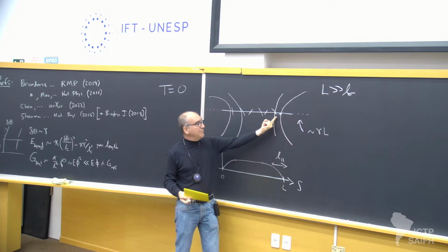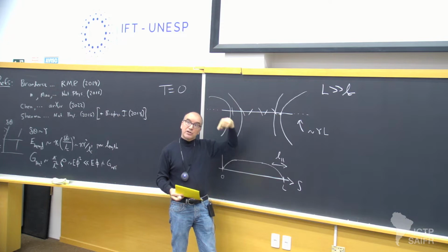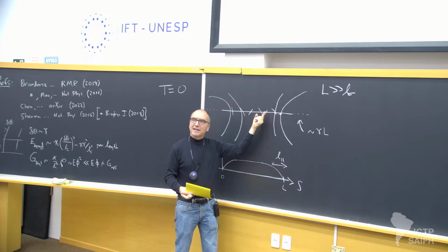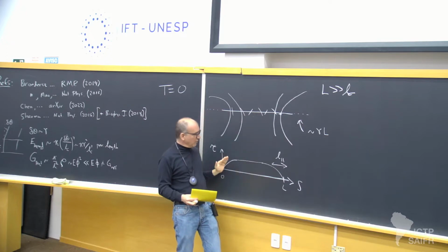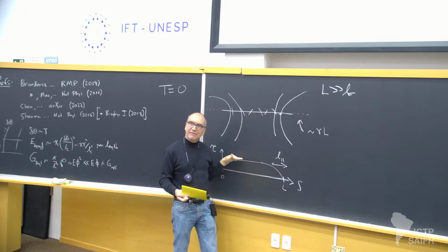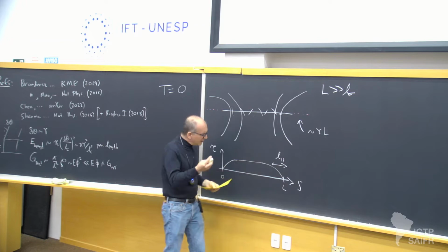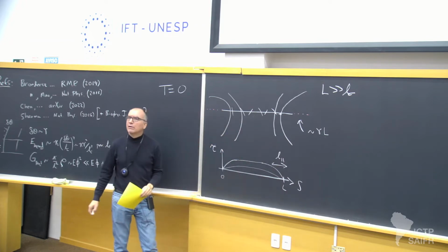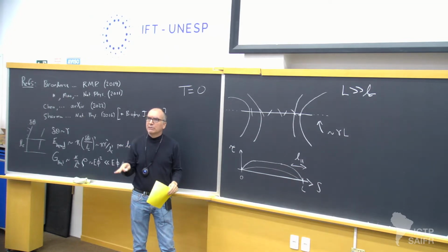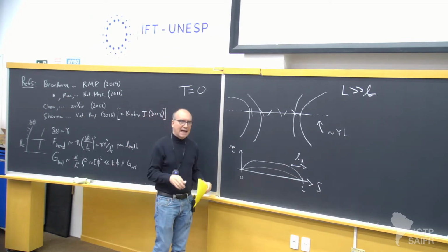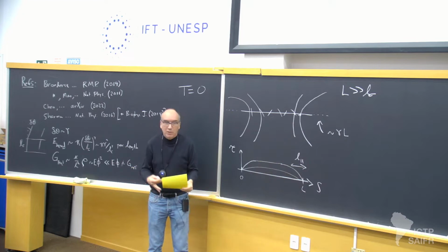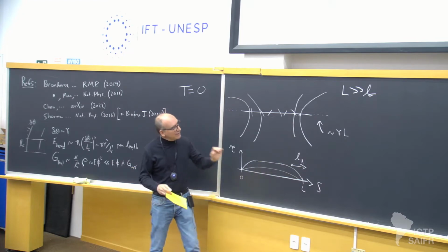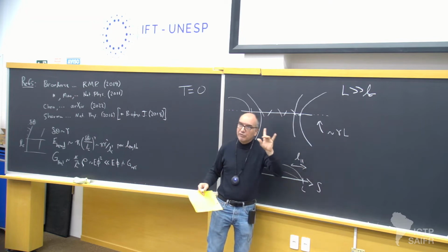And notice as I go deeper in from the edge, that tension's going to go up because I've got other neighbors which are pulling on it. You see that? So that's why it tends to grow at the edge, typically flat in the middle at high molecular weight. At modest molecular weights, it'll be more like a sine mode, okay? And it won't have a flat region. And in the extreme case of low enough molecular weight, I won't generate any tension at all. But I'm particularly interested in the high molecular weight limit because there's some new physics there, okay?